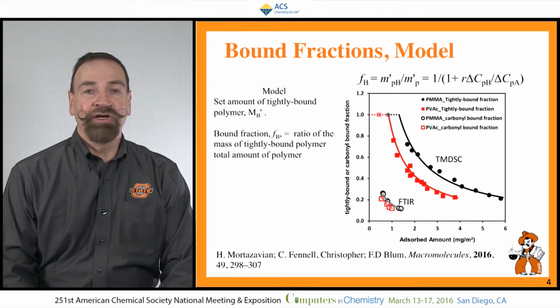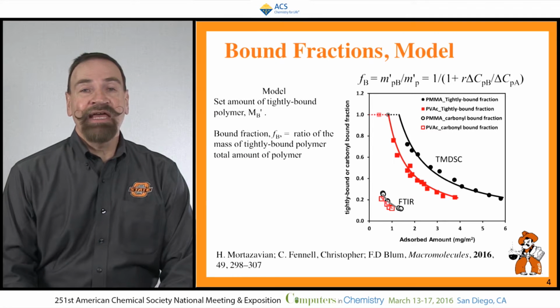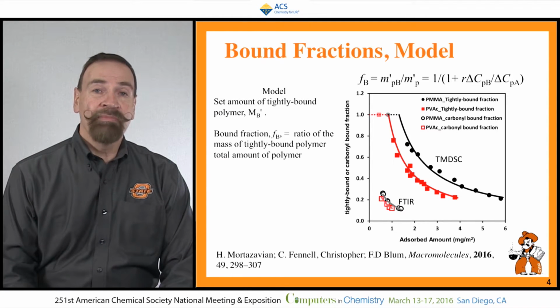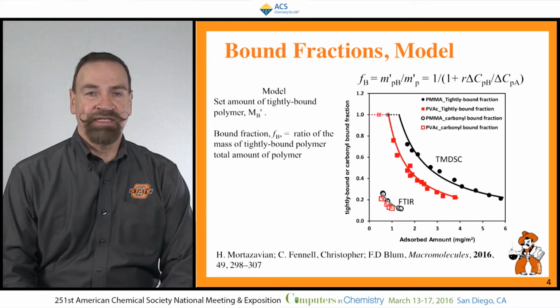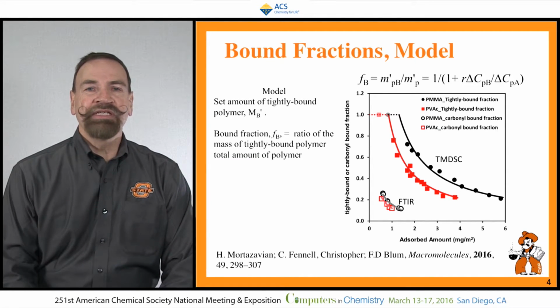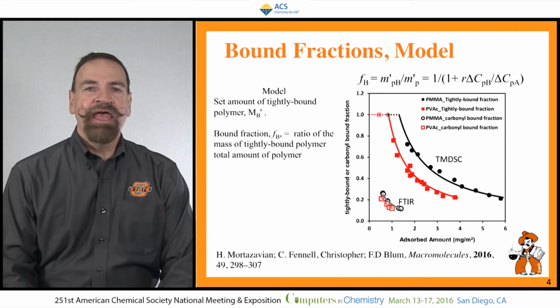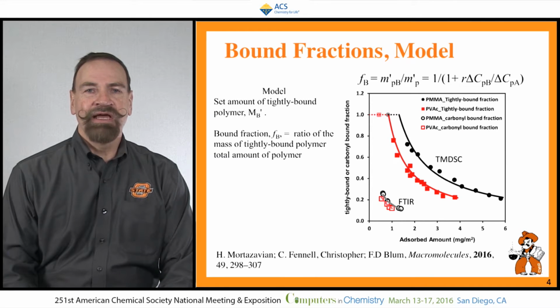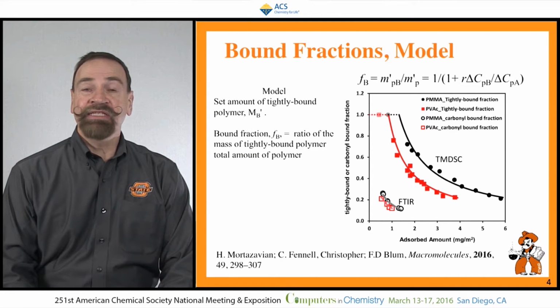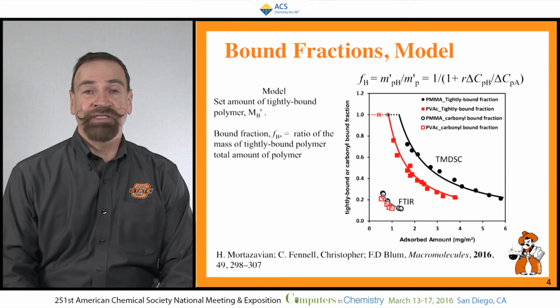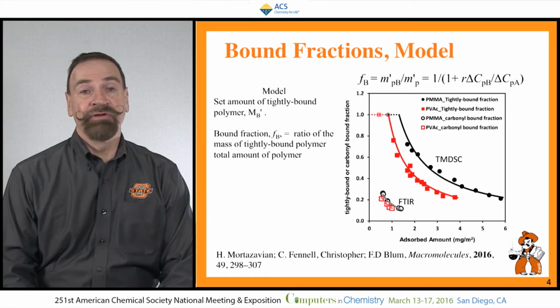A similar model is also shown for polymethyl methacrylate. In the case of polymethyl methacrylate, there's more tightly bound polymer than there is for polyvinyl acetate. On the lower portion of the curve, you'll see similar kinds of calculations for FTIR, and FTIR shows a much smaller amount of bound carbonyls. In the DSC case, we're looking at segments which tend to be motionally altered. In the FTIR case, we're only looking at carbonyl groups which are directly hydrogen bonded to the surface, and consequently, there's a smaller amount of bound carbonyl groups than there are segments which are motionally altered by the hydrogen bonding of the carbonyl groups to the surface.